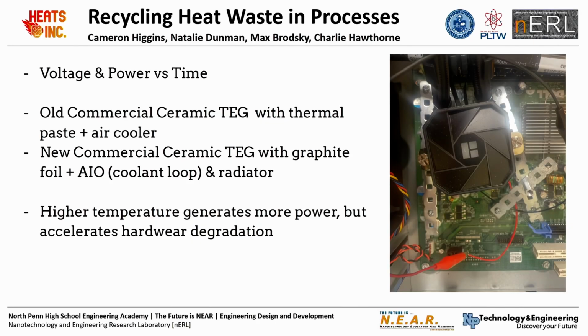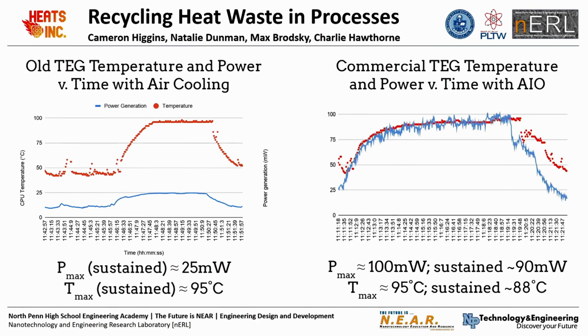We also found that the higher temperature difference can lead to advanced material degradation. You don't want your computer to be sitting at 100 degrees Celsius all day. That's bad for it. So it's important to balance those statistics to get a balanced production of electricity. You can see here, like I said, at the same temperature difference, we were able to get 4 times the power using better cooling and thermal interface materials because we reduced the bottlenecking. Like it's 90 milliwatts versus 25.